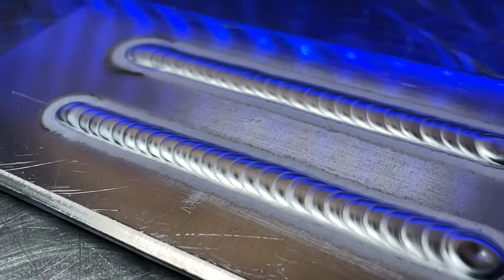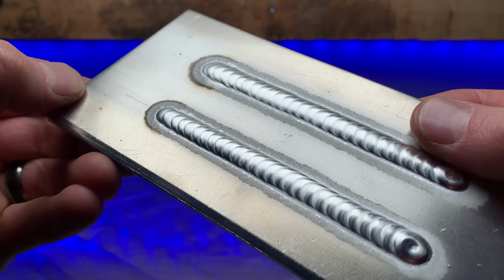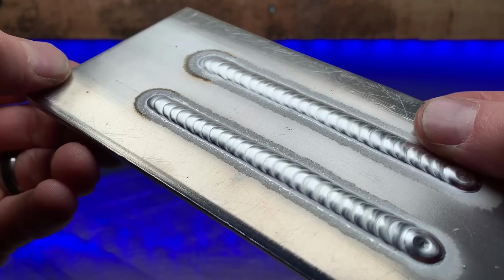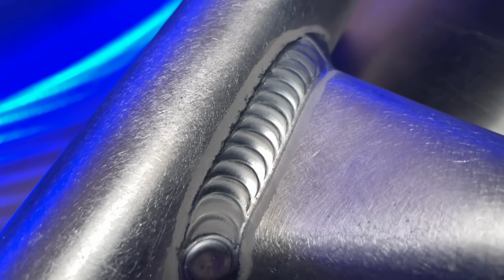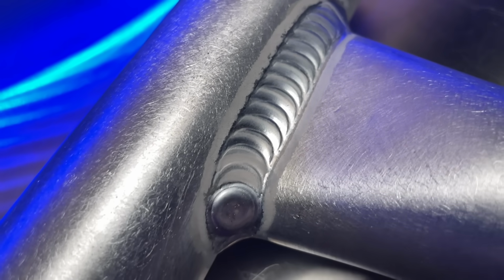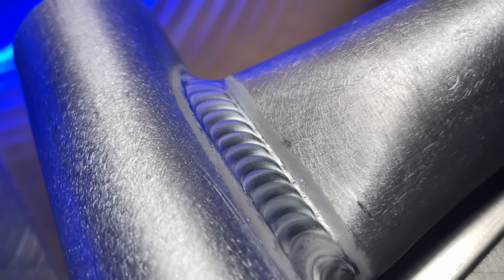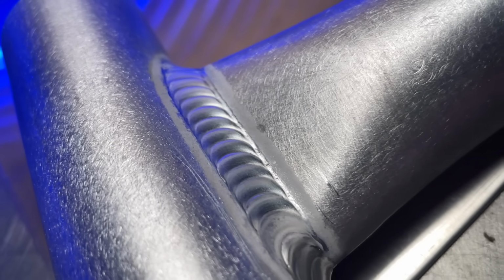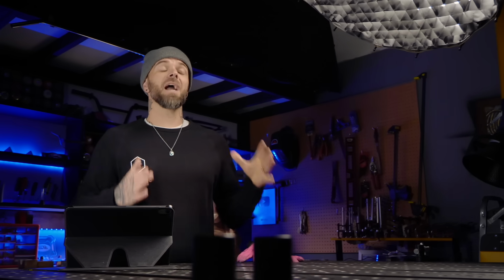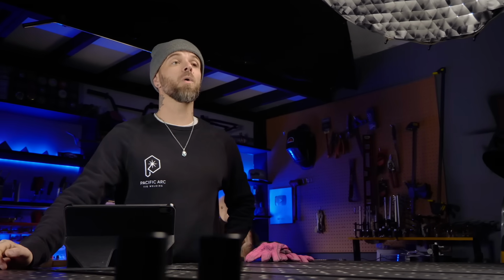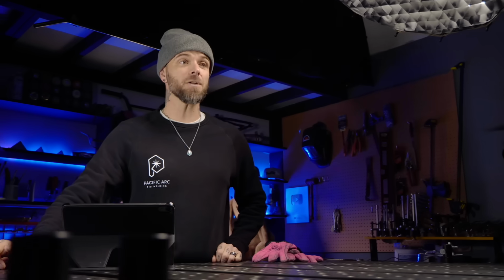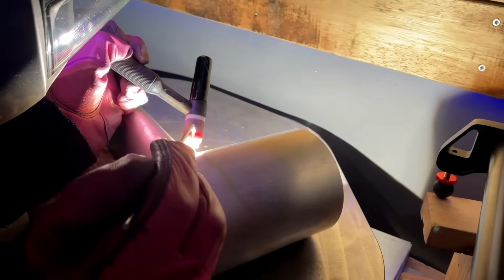Now, when working on basic plate joints, you might not particularly notice much of a difference with this at all. But like I said, with more advanced or tricky joint configurations, you are going to notice your puddle is going to be pushed around or a little less stable if your gas settings are especially too high. If your gas flow rate is excessive and you are going around corners on stuff like this here, you are definitely going to notice that all of a sudden your puddle is going to become excessively wobbly.